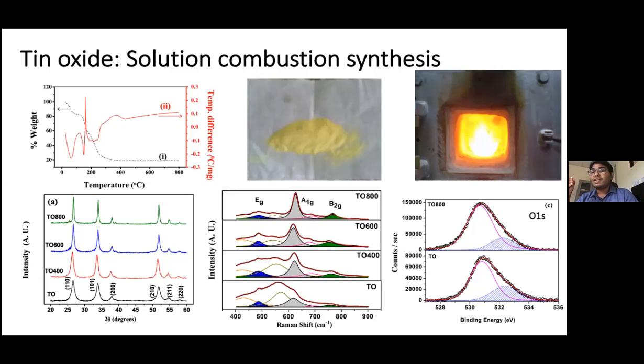So whatever defects can form at higher temperature for that flash of time, it basically forms, and it gets quenched to room temperature. And then if this hypothesis was correct, then if we heat treat the sample to higher and higher temperature, we should actually anneal all these defects, because the thermal energy is going to bring in some kind of order into the system, and that will anneal these defects, and you will get much better crystal.